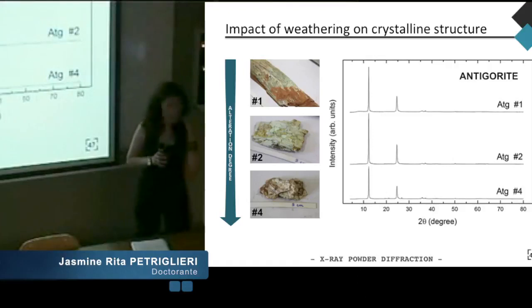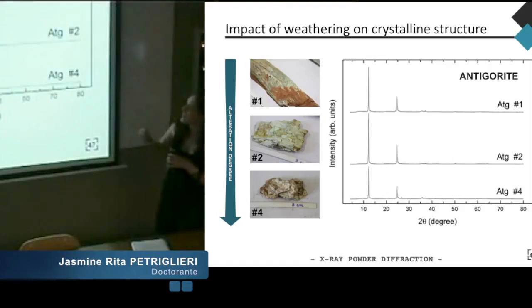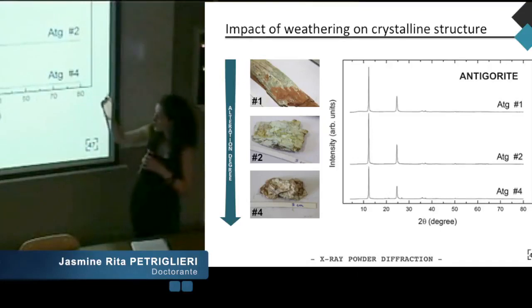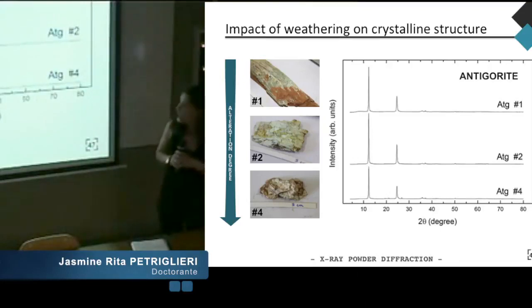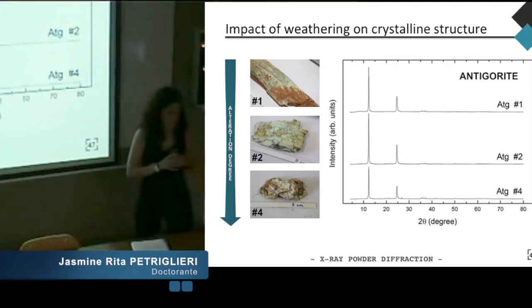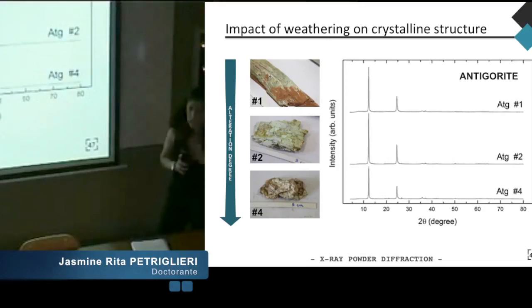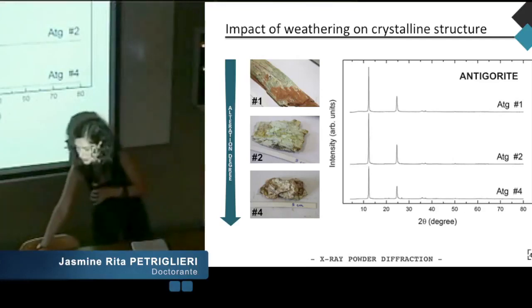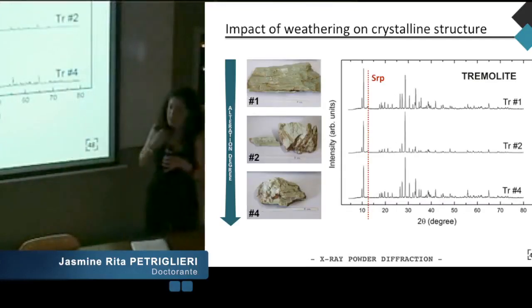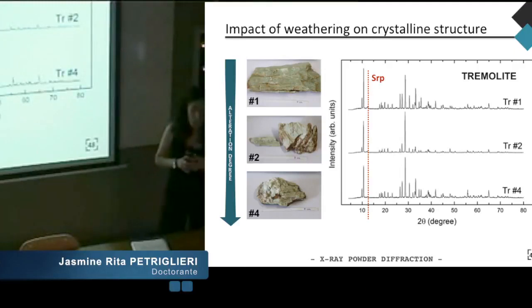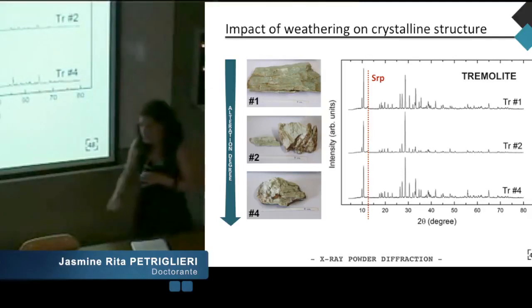As clearly evident in the slide, increasing the degree of alteration from 1 to 4 for the antigorite samples, the diffraction patterns show completely comparable. No modifications are observed in the peak position, in the peak broadening, or in the intensity. This is true for antigorite and for tremolite samples, and this suggests that weathering does not impact the crystalline structure. Probably weathering impacts the chemical reactions at the surface.